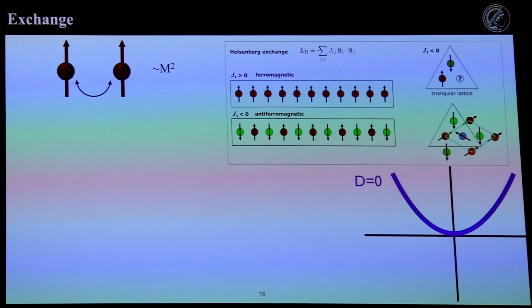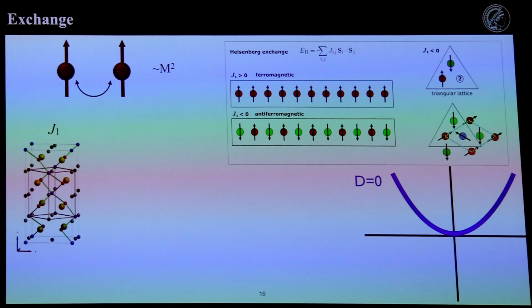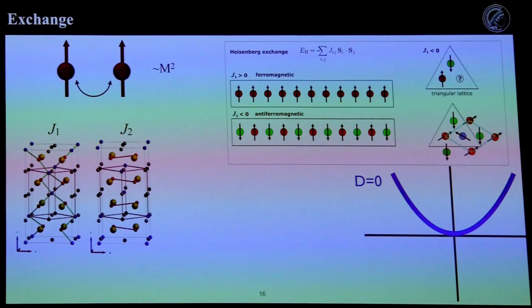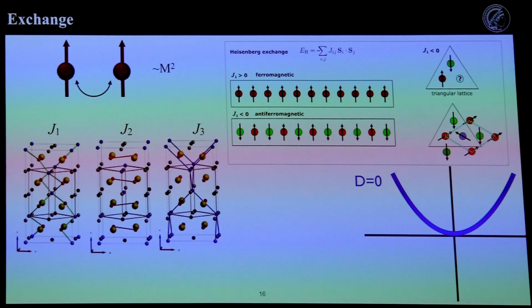And without any D, it's not so interesting, but there are other cases when you start to put in different neighboring interactions of exchange. So there is the first nearest neighbor exchange for these manganese platinum tin compounds, which is shown here. It was the same crystal structure as before. This pink line here is the manganese platinum tin. And then what you have is this first nearest neighbor interaction, which is the green, and then you can put in another case, which is this second nearest neighbor interaction, and the third nearest neighbor interaction.